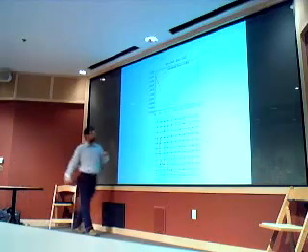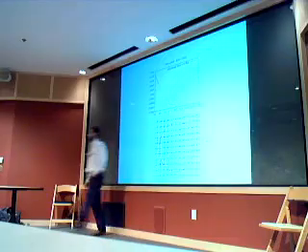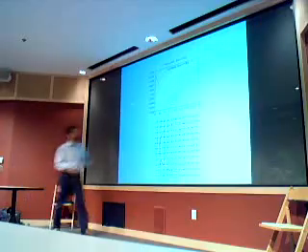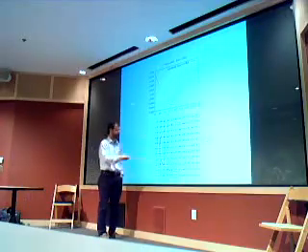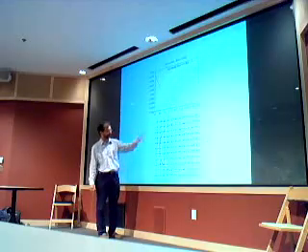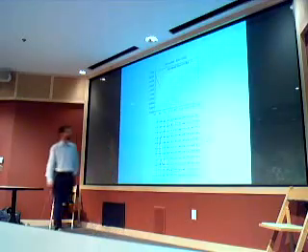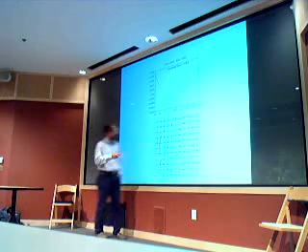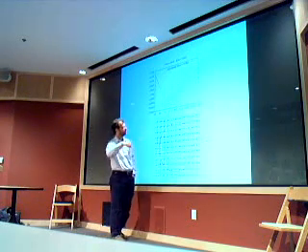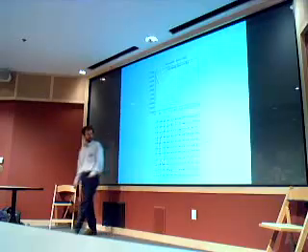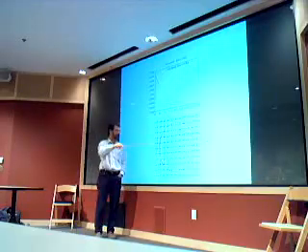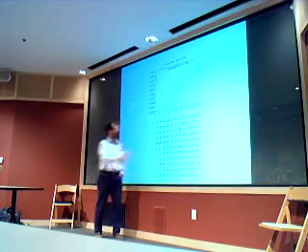Well, the problem is related to the fact that we are using plane waves, and these calculations are done using a constant cutoff. So when you have a certain cutoff, you have your Bravais lattice, you have the reciprocal lattice. This is, let's say, the reciprocal lattice for a cubic system or a square system. And our recipe is that our basis set corresponds to a set of plane waves whose cutoff energy, so whose square moduli, are less than a given cutoff.